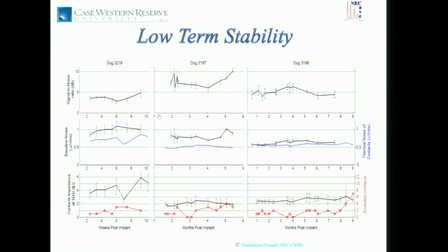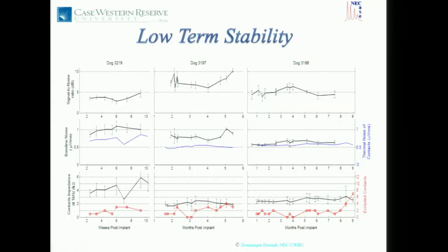The baseline noise is consistently below 1 microvolt RMS, and in some cases even down to 0.5, which is, I'd say, some kind of record on a fully moving animal. I don't think it's ever been done. Keep in mind also that the source electrodes have their own source resistance, right? They're not infinitely big, they're small. The smaller they are, the larger the impedance of the electrodes. That by itself creates its own noise, that's Johnson noise. It's just the noise of an impedance. And so these numbers include the electrode noise and the amplifier noise as well. The impedance of these electrodes was quite stable, about 2K or so, which creates by itself maybe 0.3 to 0.4 microvolt RMS. So you can tell from this that the noise of the electronics is almost 0.